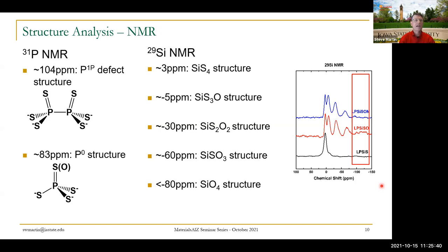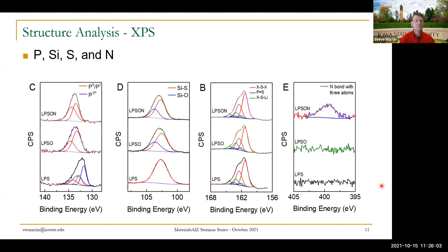But suffice it to say, at this stage, we've got a very good handle on what the underlying atomic level structure is of these nominally amorphous materials. They have beautiful structures at the short range order. Long range order, yes, they're not crystalline, but the short range order is quite well defined. And honestly, with advanced spectroscopies like NMR, we can identify them in a fairly straightforward manner.